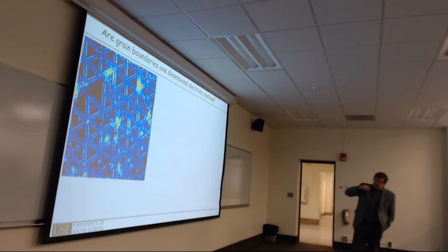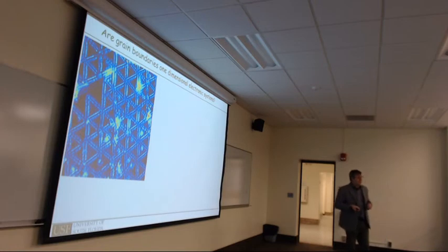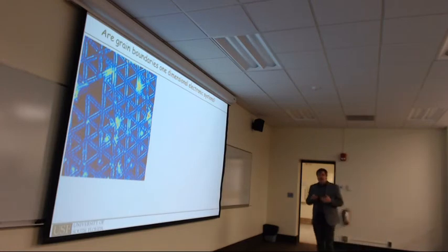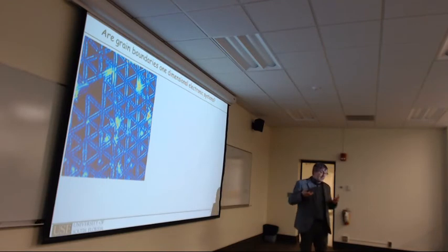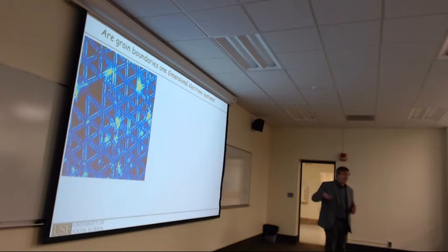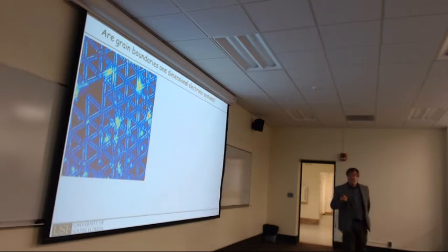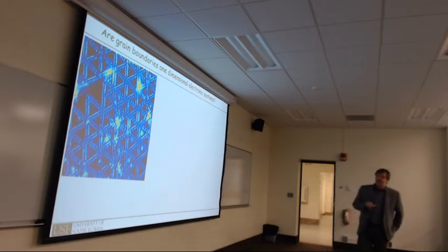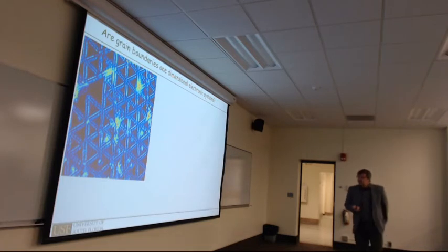Right. Now, clearly they appear bright in STM. And that's because molybdenum diselenide is a semiconductor. In STM, you have electronic contrast. So if you have a metallic line in the semiconductor, the metallic line will appear much brighter than the semiconductor. So just the contrast in the STM image suggests that this is really a metallic line.